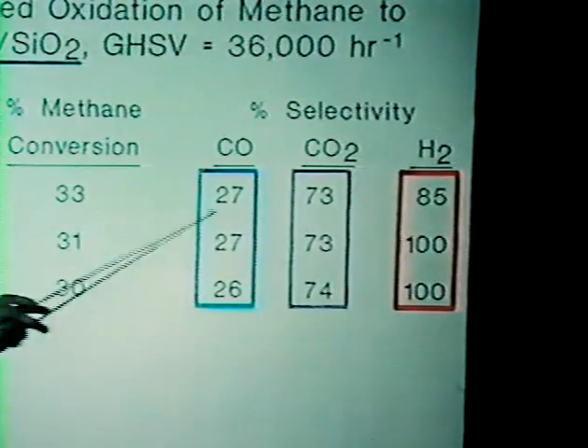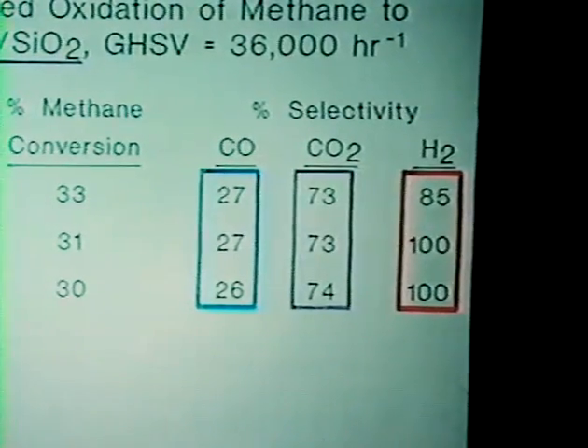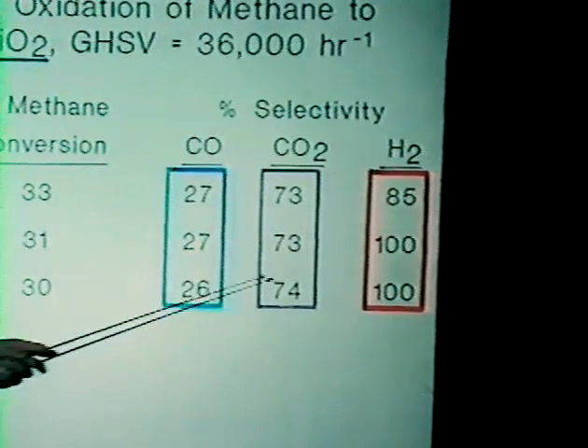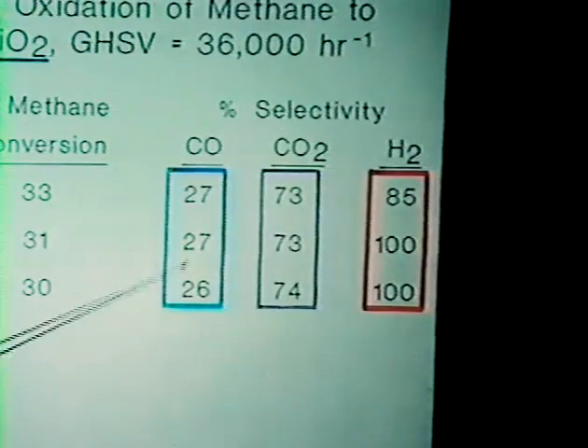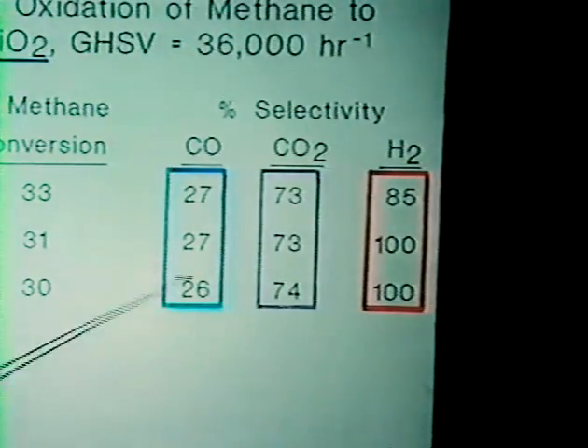Now, the CO-CO2 ratio is not quite satisfactory. You might want to control that ratio. You might want to make more CO and less CO2, for example, or more CO2 and less CO, depending. So how do we control? What is the catalytic principle for controlling CO-CO2 ratio? Obviously, the first thought, supported by experimental evidence, is that what you have prior to the CO-CO2 oxidation is surface atomic carbon. How do you control oxidation of surface atomic carbon to CO versus CO2?